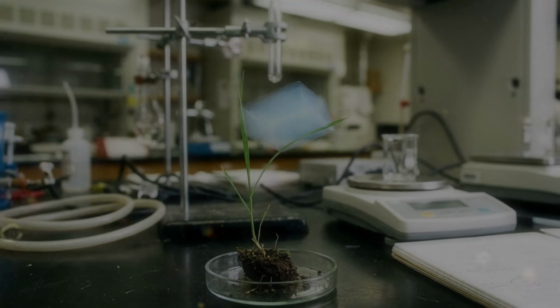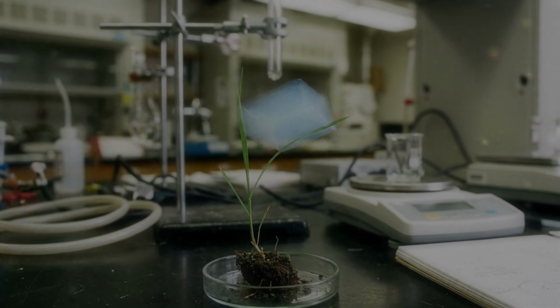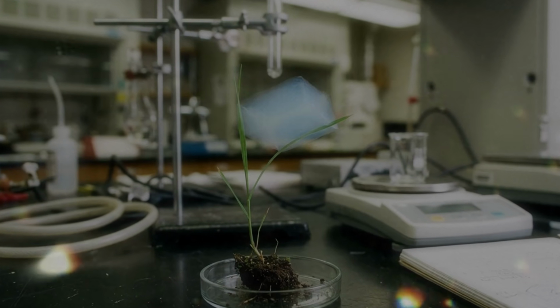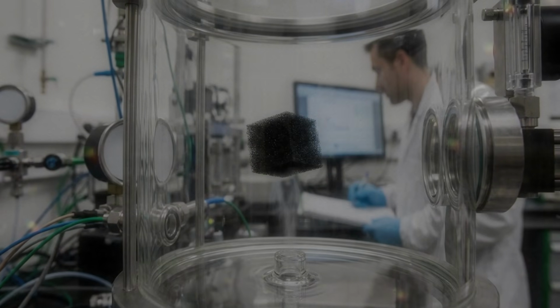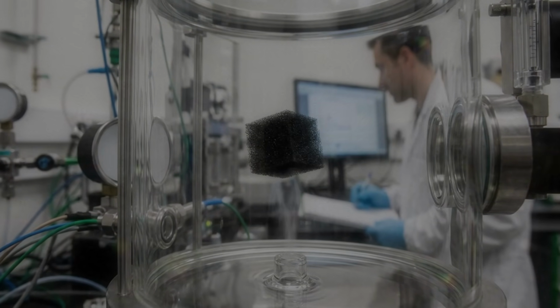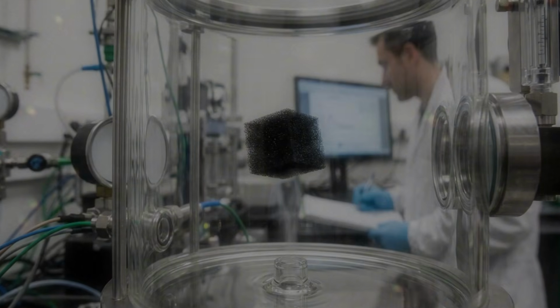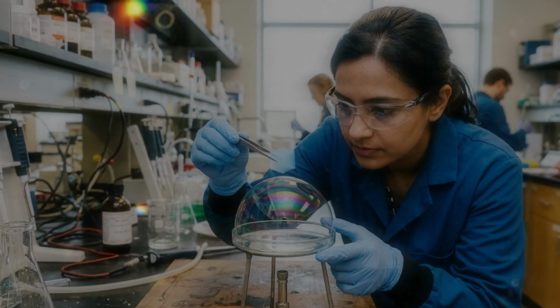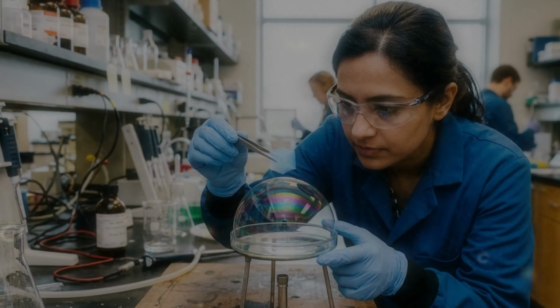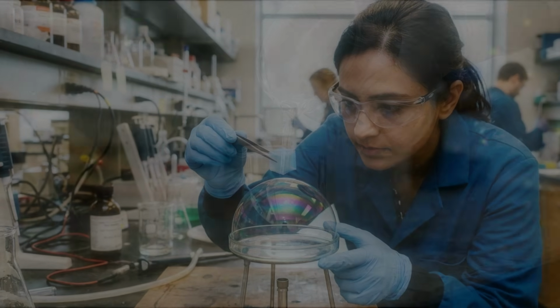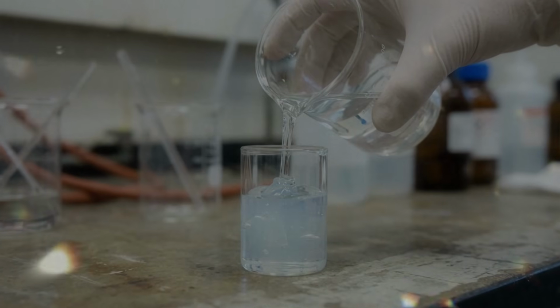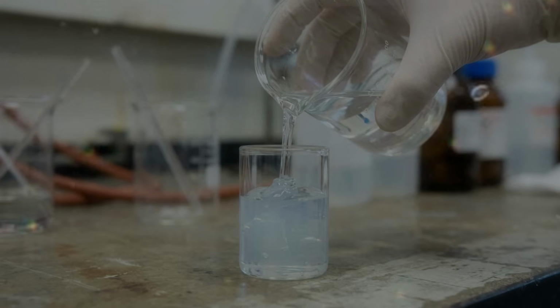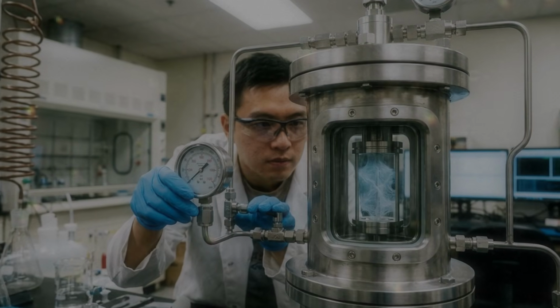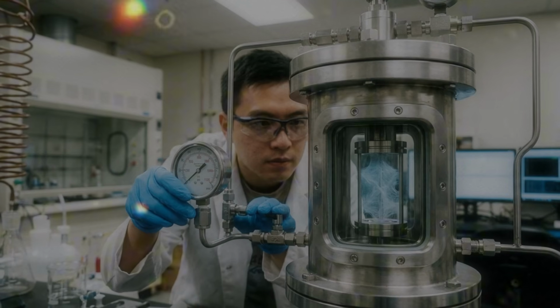Some graphene aerogels contain chemical links between neighbouring sheets. These links stop the sheets from separating too easily. Others use reinforcing fibres, nanotubes or polymer chains. Printed microlattices can place material in repeating patterns instead of leaving the cells entirely random. A regular lattice gives researchers more control over how the aerogel collapses. They can adjust the width of the walls, the size of the openings, and the direction of the supports. The result may be heavier than the lightest possible random aerogel, but it can be more reliable.